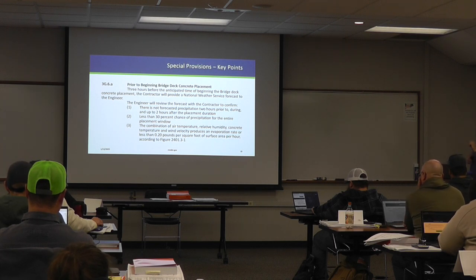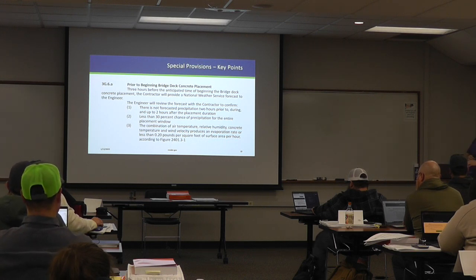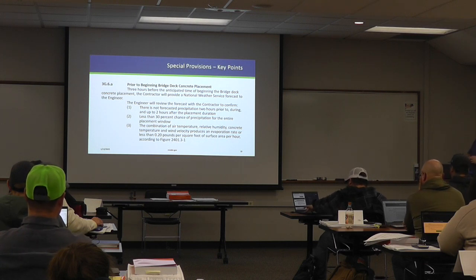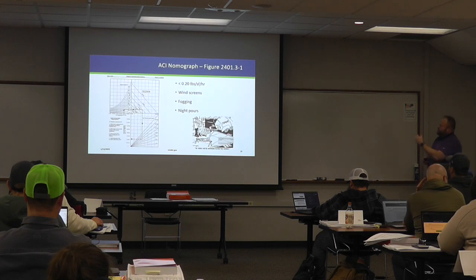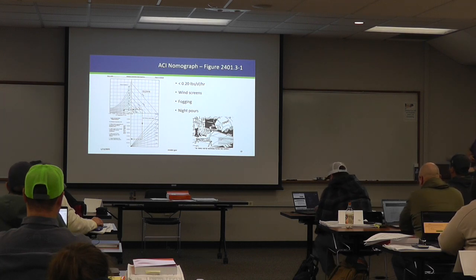One thing to point out though is that I have seen in some of the silica fume overlays that this is not 0.2, it's actually 0.1 or 0.15. So if you're ever on a silica fume overlay project, just double check what the evaporation rate requirement is. But yeah, this nomograph is in the spec book, and this is how we would determine what our evaporation rate is 3 hours prior to. I'm also developing an Excel spreadsheet that we can use, which would make this a little bit easier.